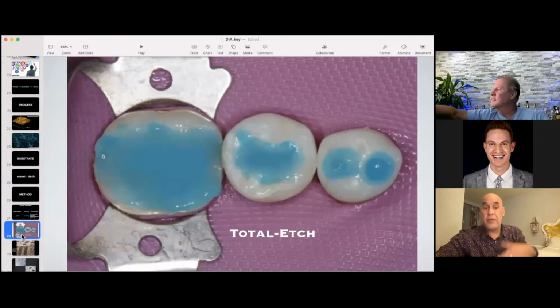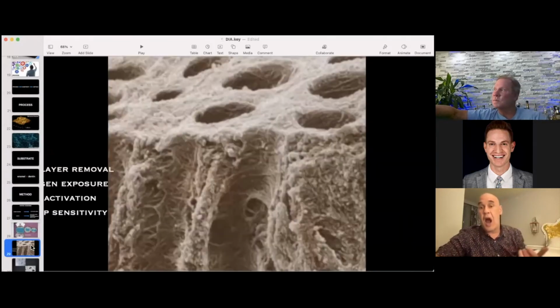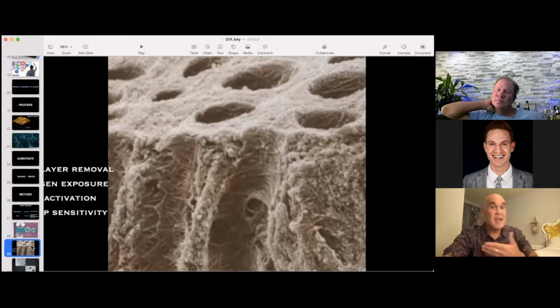What are you doing here? You're removing the smear layer. But when you remove this smear layer, you're also exposing collagen and opening up the tubules. This is unavoidable. The removal of the smear layer by phosphoric acid, whether it's 32, 35, or 37%, is going to happen within 5 to 7 seconds of etching. So when people are etching dentin for 30 seconds, that's overkill. You can etch 15 seconds and you're going to be fine.